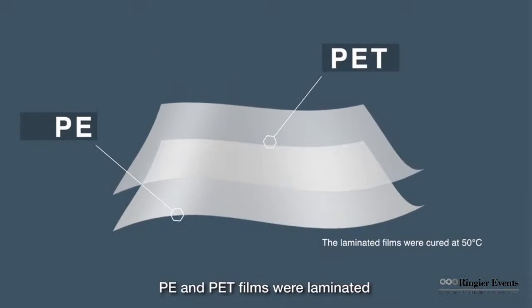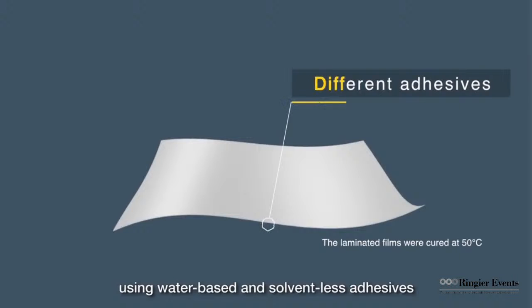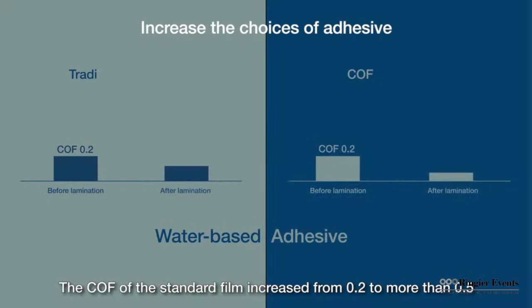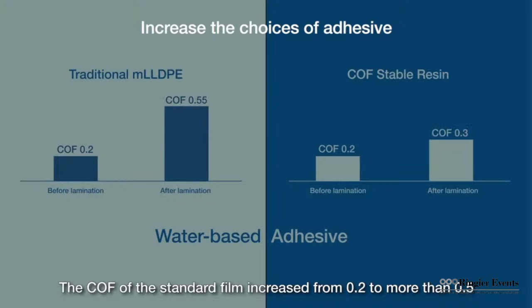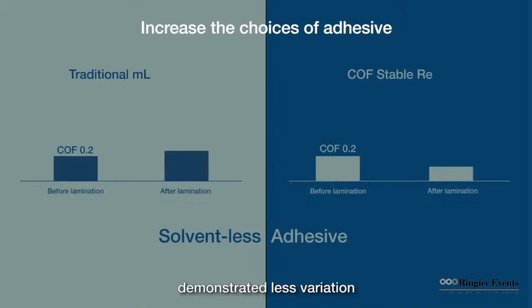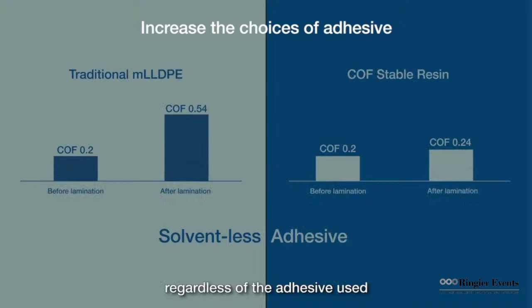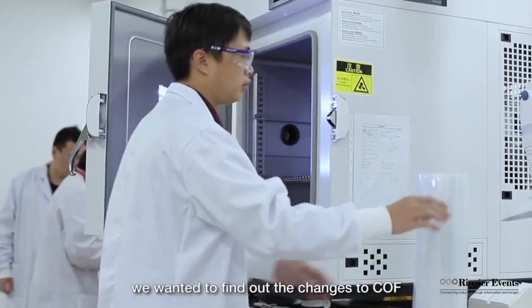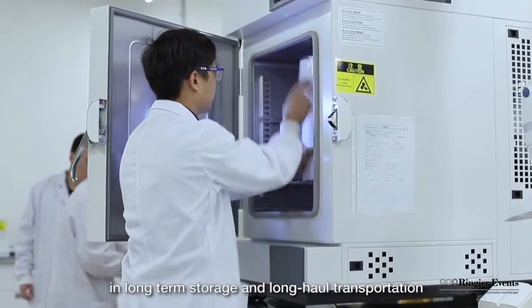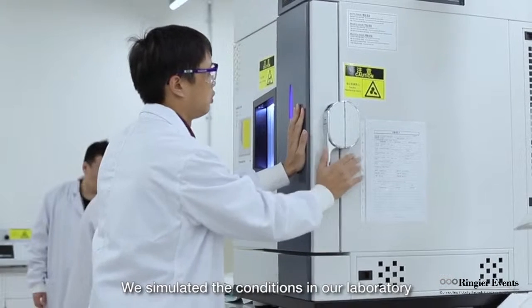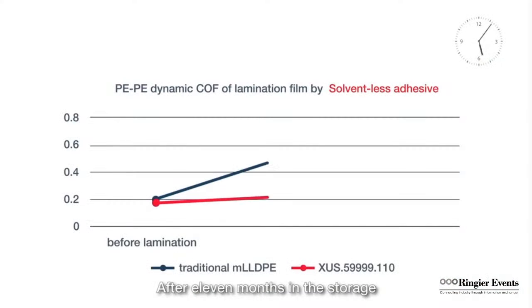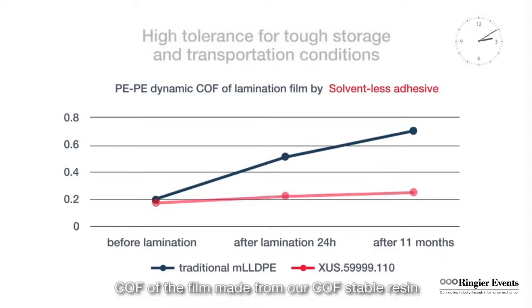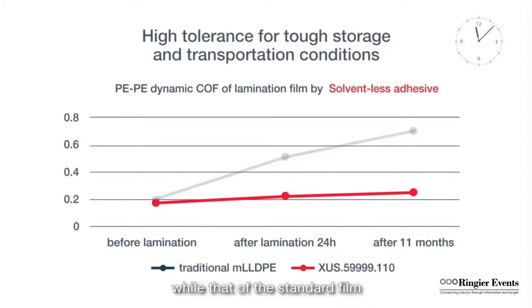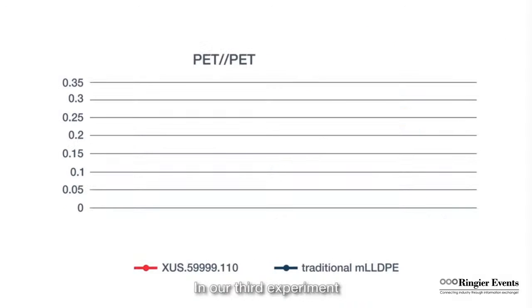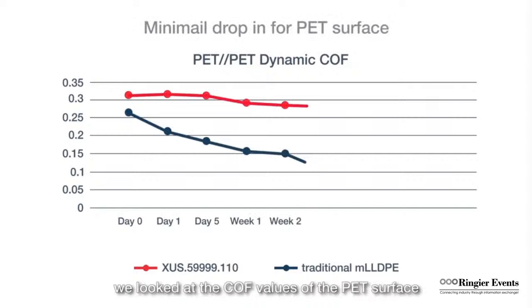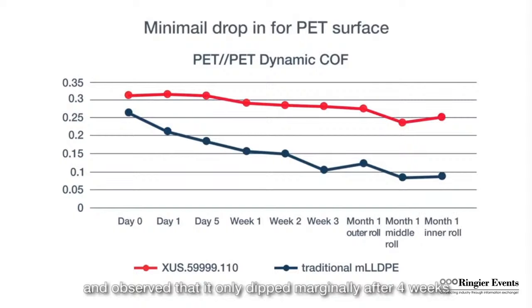In our first experiment, PE and PET films were laminated using water-based and solventless adhesives. The COF of the standard film increased from 0.2 to more than 0.5, while the film made with the COF stable resin demonstrated less variation regardless of the adhesive used. In our second experiment, we wanted to find out the changes to COF in long-term storage and long-haul transportation. We simulated the conditions in our laboratory. After 11 months in storage, COF of the film made from our COF stable resin remained almost at the same level, while that of the standard film dramatically increased by more than 0.5. In our third experiment, we looked at the COF values of the PET surface and observed that it only dipped marginally after 4 weeks.